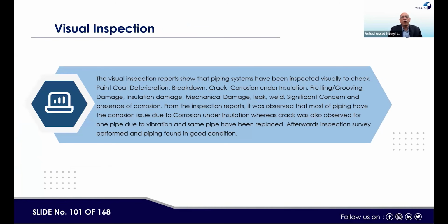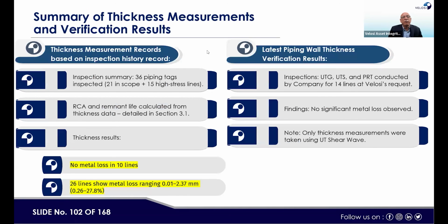Then visual inspection results, like what kind of troubles are there. CUI related issues were seen a lot, and then there were certain issues on the piping supports because of high thermal movements. Those were kept in good shape, but there were indications that some problems were caused by the thermal movements of the piping system on the piping support side as well. Since there is high temperature to low temperature cyclic service, CUI is a problem, and somewhere the cladding was also removed to deal with the CUI problems. Here, in the thickness measurement records, we found that for 10 lines there was no metal loss, but 26 lines show metal loss ranging from 0.01 to 2.37 mm, basically from 0.26 to 27.8% metal loss.